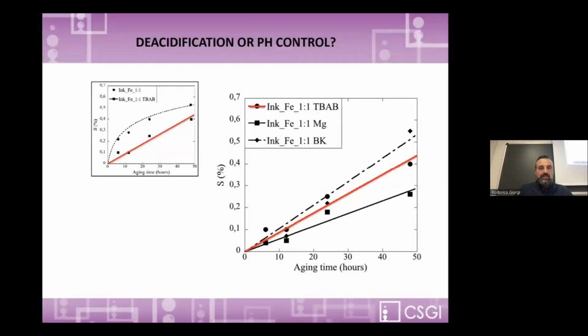If we look at the effects of a deacidification, I say deacidification, but better to say pH modification to get pH around neutrality, between 7 and 8, we can see that the same behavior we obtain using antioxidant is obtained simply by modifying the pH. You can see here that the two curves in the larger graph refer to the application of, in this case, magnesium hydroxide, compared with the Bookkeeper method. You know, Bookkeeper uses magnesium oxide, which turns into magnesium hydroxide. So at the end, the neutralizing agent is the same. And you can appreciate that we have the same benefit we have applying antioxidants.